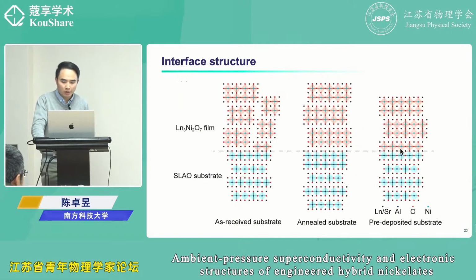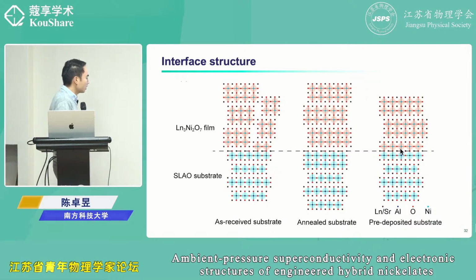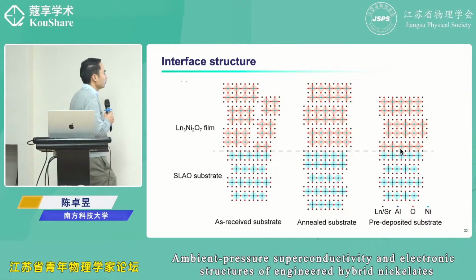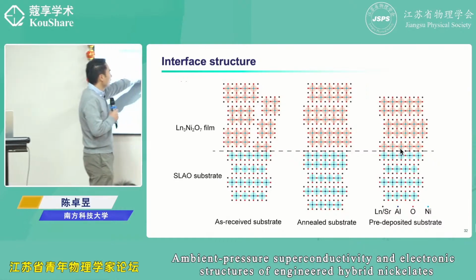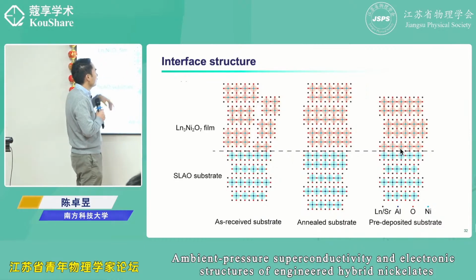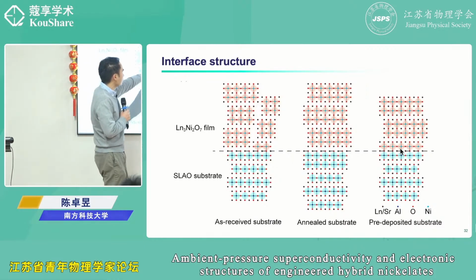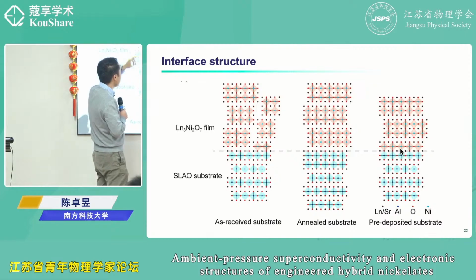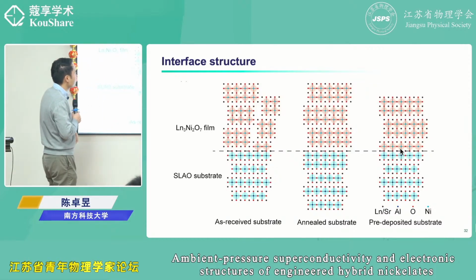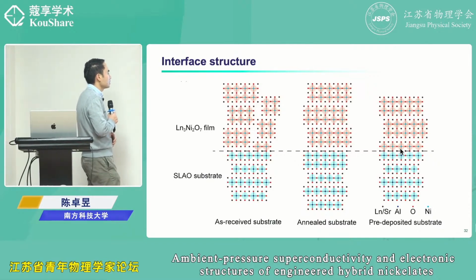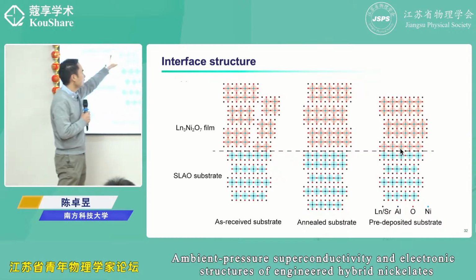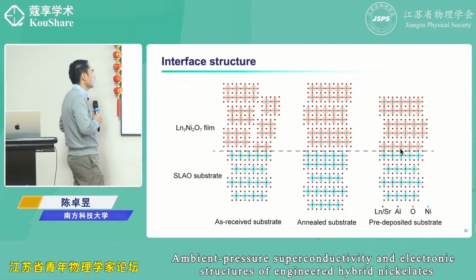Another trick that we used is interface structure management. Usually, if you use the as-received substrate, it's a 214 structure, so you have a single layer on top. If you grow the bilayer directly, some may form this nickel aluminum bilayer, some may grow directly, so you have different modes with similar energy. They may coexist and make the film not so crystalline coherent.